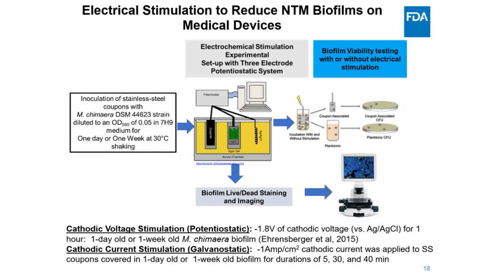Following this stimulation, we evaluated the biofilm viability by measuring the colony-forming units from both coupon-associated bacteria as well as planktonic bacteria from the solutions. We also performed live/dead staining to visualize the viability of these biofilms using a fluorescent microscope. This approach allows us to assess how well electrical stimulation reduces viable biofilms both on the surface and in the surrounding solution.